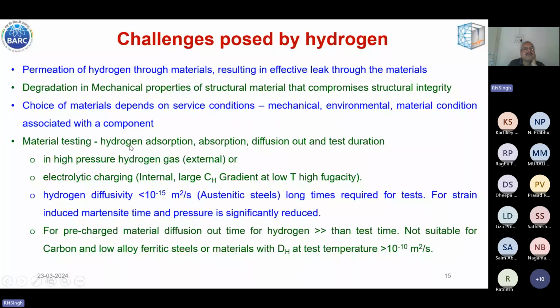The material can be directly tested in high pressure hydrogen gas. It is an external source of hydrogen, or the material can be pre-charged electrolytically with hydrogen, and the test can be carried out. Hydrogen diffusivity is very important. Like for austenitic stainless steel, the diffusivity is less than 10⁻15 square meters per second. So a long time is required for hydrogen charging itself.